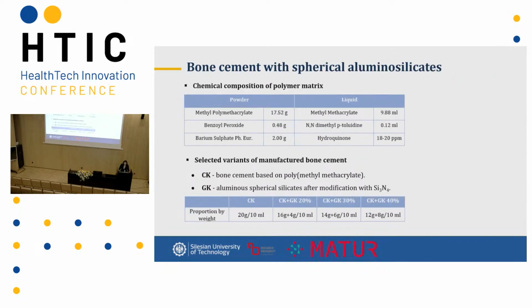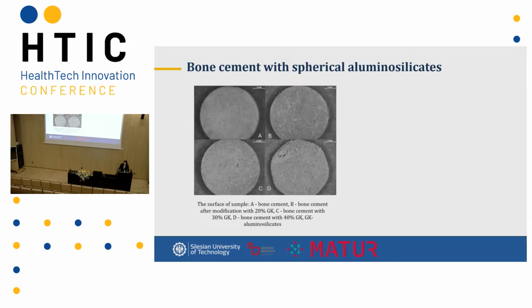So, in my research, I chose a PMMA matrix and made three variants of the combination with 20, 30, and 40% amounts of spherical aluminosilicates with modification. This is how it looks. A is PMMA without the aluminosilicate. B, C, D are 20, 30, and 40% amounts of microspheres.